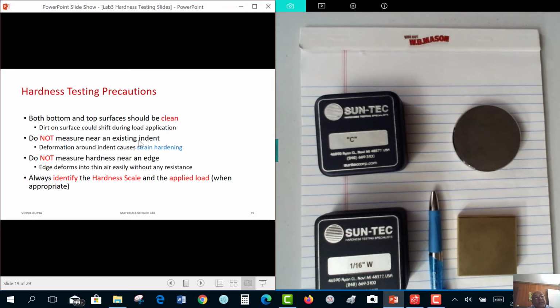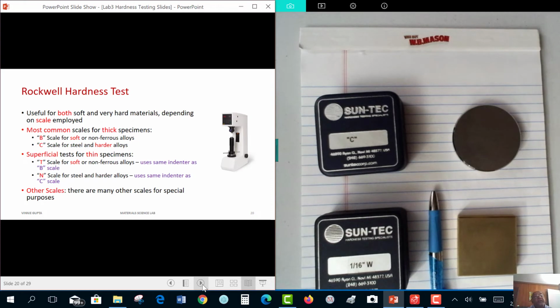Of course, do not measure near an existing indent because the area around an existing indent is strain hardened. Do not measure near an edge because the edge does not provide any support, so the material is going to appear softer. And always identify the hardness scale with the number and applied load when it is appropriate. So for T scales, you remember you have to say whether it was 15 kg, 30 kg, or 45 kg. But for C scale, you will find out soon that the load is constant, so you don't need to specify it.